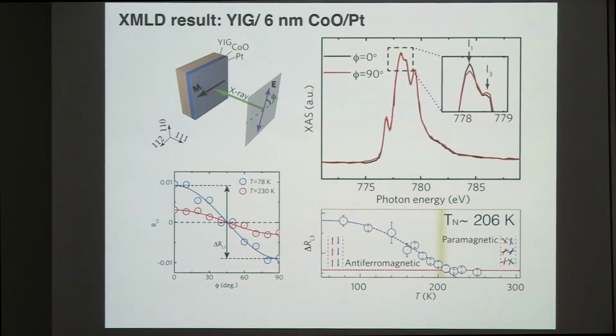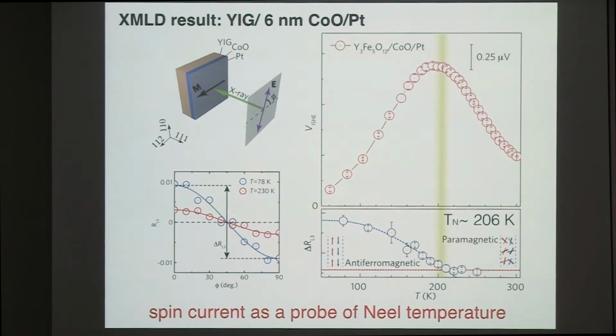The red and black curves represent the spectra we get from the linearly polarized light perpendicular and parallel to the magnetization of YIG. We can see that there really is some finite contrast. So our collaborator plotted this difference against the temperature. Finally, he found that the Néel temperature is somewhere here, and we compared this to our data. It's a pretty good agreement.